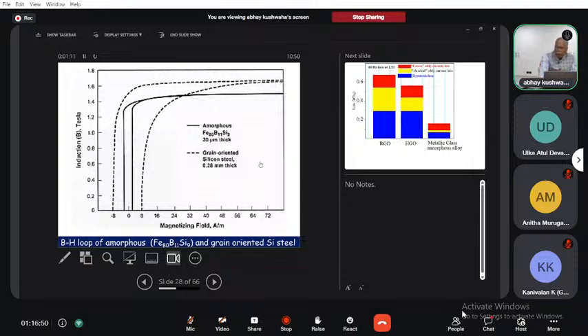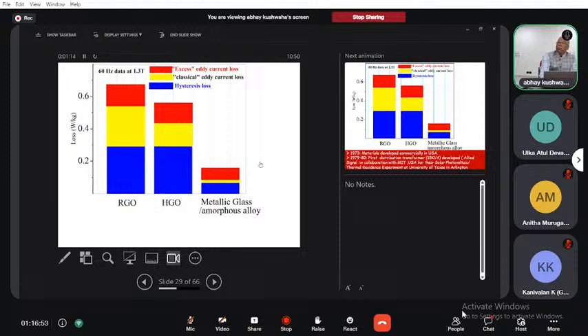And if we now compare this material with the regular grain-oriented and highly grain-oriented steel, and we have the amorphous alloy or the metallic glass, whatever you call it, the loss for the highly grain-oriented, which is around 0.55 watts per kg, is reduced to less than 0.2 watts per kg. I can understand how much is the reduction in the hysteresis loss, how much is the reduction in the eddy current loss, both excess and the classical eddy current loss.